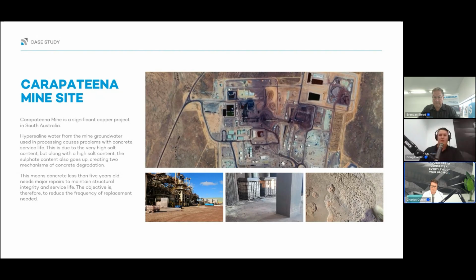Now, this particular site, they used an admixture in the concrete, a traditional admixture, but they were having real problems with the workability and set times of it. So they switched across to a hydrogel admixture, which is neutral on set times, and did essentially the same waterproofing job, but because you could get a better quality result, or pour, the finishers preferred placing it, everything like that, we're seeing a lot longer service life coming out of that environment than what they were using.